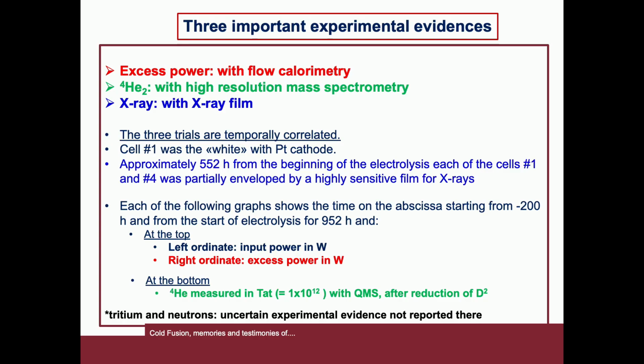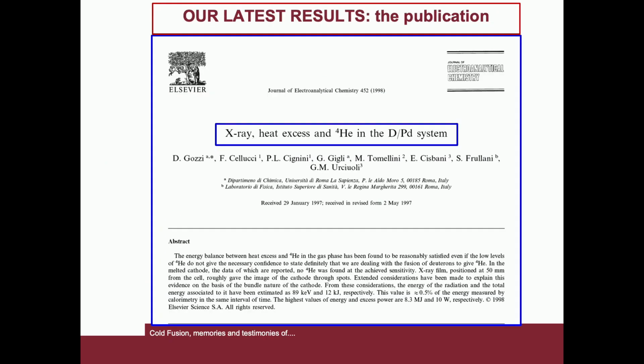It was a complex experiment which lasted 952 hours with 4 cells identical in structure, 3 of which with a palladium cathode, but each with a different geometry, and the other as white cell with platinum cathode. At 552 hours from the beginning, the blank cell number 1 and cell number 4 were wrapped with X-ray film. The results of our latest experiment were reported in the article entitled X-ray, heat excess and helium-4 in deuterium palladium system. It was published in the Journal of Electroanalytical Chemistry. The first page of the article is reproduced here.